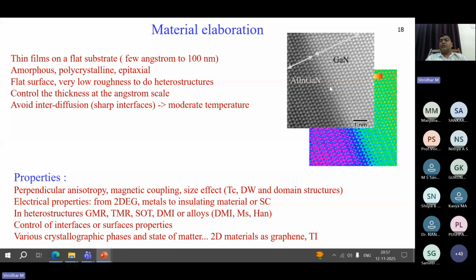Okay, sometimes what happens, the defect formation will be more. So as you control the atmosphere, the defects will go down. As you decrease the defects, then only you can use these materials in any applications like sensors or creating PN junctions or solar cells and all. Whatever solar cells we have in the market will have too many defects. But these are large scale solar cells that we are using. That particular defect will not contribute to the total outcome of the solar cell. Suppose it is giving you 1 kilowatt in one day, a small defect will not reduce the power generation. But when you see a 1 centimeter by 1 centimeter device, a small defect will cause devastation. It gives very bad results.